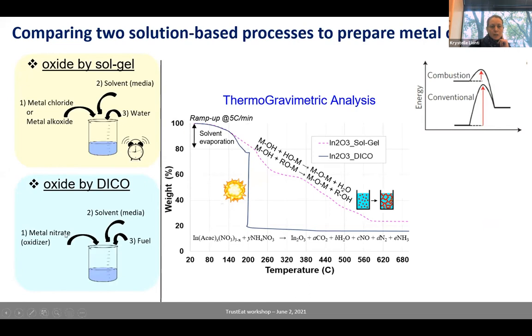And so the Sol-Gel chemistry one is also known as soft chemistry. It is a continuously evolving process that relies on hydrolysis and condensation reactions, which I'm showing here. And so these reactions start as soon as the precursors are mixed together and typically proceed rather slowly at room temperature. And they slowly build up a 3D network over time. So this is what I'm showing here. We start with a solution that has individual molecules, and then through condensation reactions, we have the 3D network of the oxide that's forming. In order to speed up the condensation process, we can heat up our system. And typically it takes temperatures as high as 400 degrees Celsius for an hour or even longer to reach a high level of condensation.